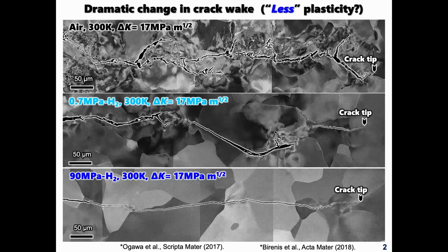So we have continuously studied this topic by performing several fatigue crack growth tests with control of gas temperature, gas pressure, loading frequency, and stress intensity factor, so as to clarify the basic mechanism from the viewpoint of hydrogen-dislocation interaction. We found the collective plasticity is drastically suppressed in gaseous hydrogen environment. As you can see, the fatigue crack goes straight without severe plastic deformation and crack wake. So we were very interested in why the presence of hydrogen suppresses the plasticity during the fatigue process. This is the motivation of our series of experiments.